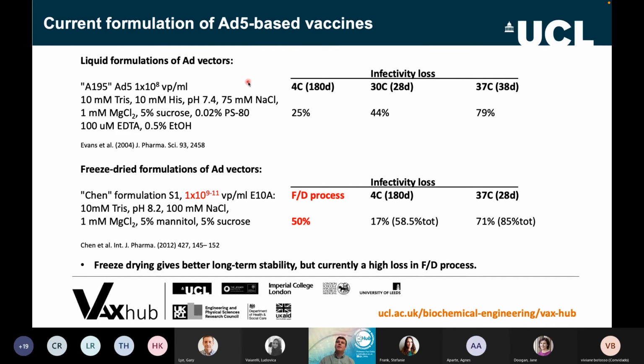So one thing I'll do is just give you an idea of where the current state of the art is. And so these are previously published adenovirus formulations. There's a liquid formulation in this paper here, Evans 2004. And you can see their survival, this is how much loss you get. Certainly at 37 degrees, just over a month, and you've lost 80% of it. In the fridge, even over 180 days, you've lost 25%.